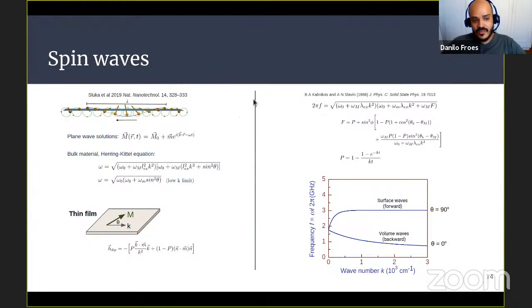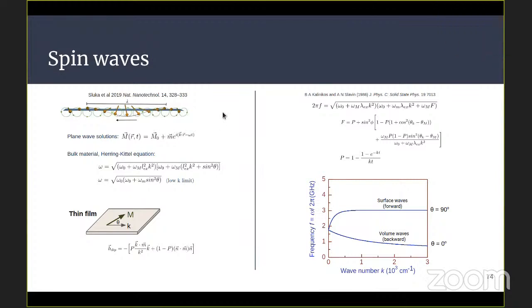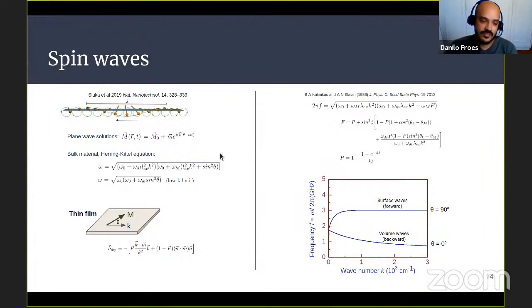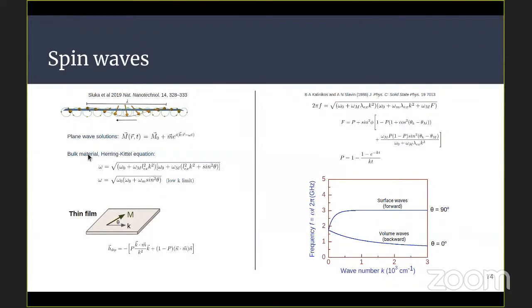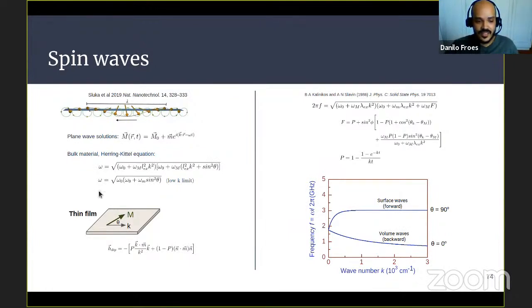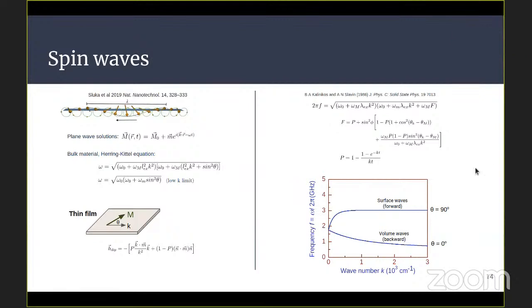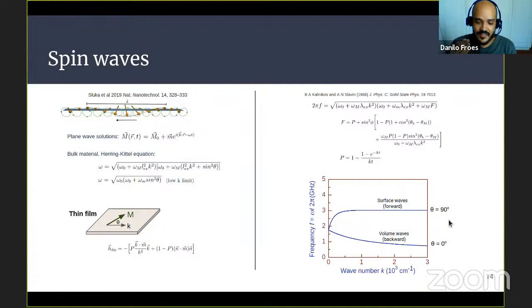When we talk about spin waves, we're actually looking for plane wave solutions in the Landau-Lifshitz-Gilbert equation, by doing Fourier transforms. So in a bulk material, an infinite material in three dimensions, this is what we get, the Herring-Kittel equation, the dispersion relation. For low K, this is what we get, the typical Kittel equation we've seen many times. And for a thin film, we have to include the effective dipolar magnetostatic energy in the equation. Kalinikos and Slavin in '86 got this solution for the plane wave, the dispersion relation for the thin film. The important thing here to highlight is that the dispersion relation is very anisotropic.